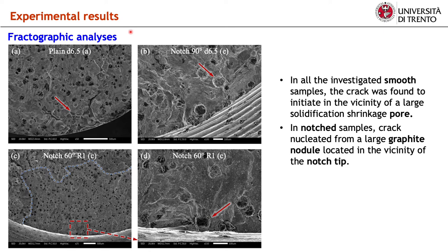SEM analyses were conducted to identify the dominant crack initiation mechanism acting in the high cycle fatigue regime. In all the investigated plain samples, the crack was found to initiate in the vicinity of a large solidification shrinkage pore. The scenario depicted by the fracture surface of notch variants is completely different. Despite careful search, no shrinkage microporosity was found in the neighborhood of any fatigue crack initiation site at the tip of the notched samples. The fracture surface reported in this figure indicates that the crack nucleated from a large graphite nodule located in the vicinity of the notch tip.